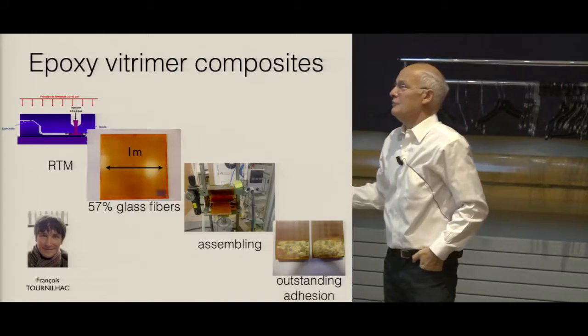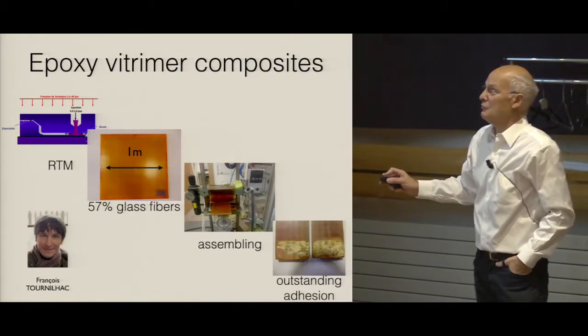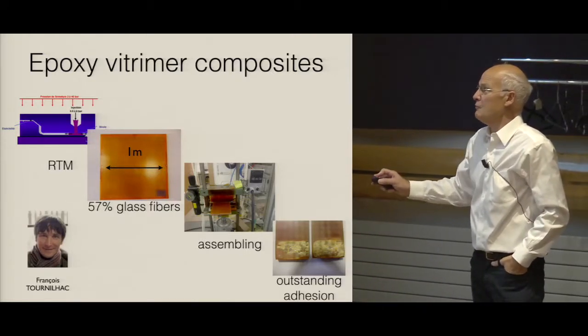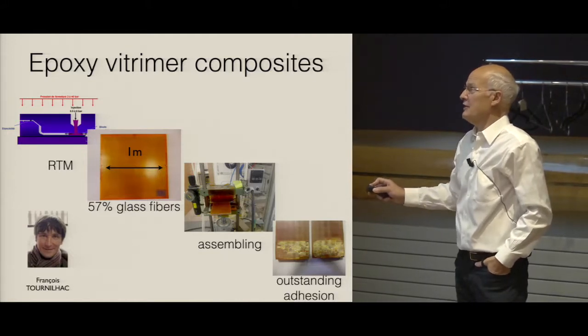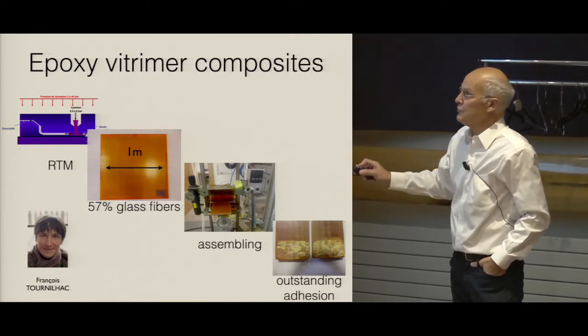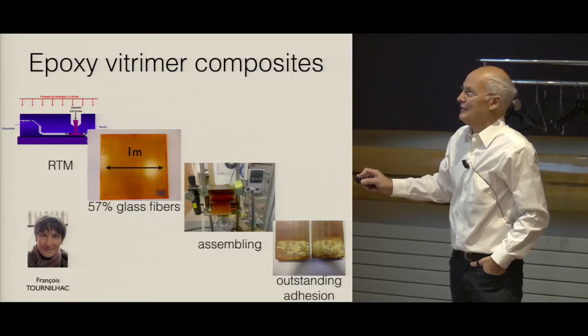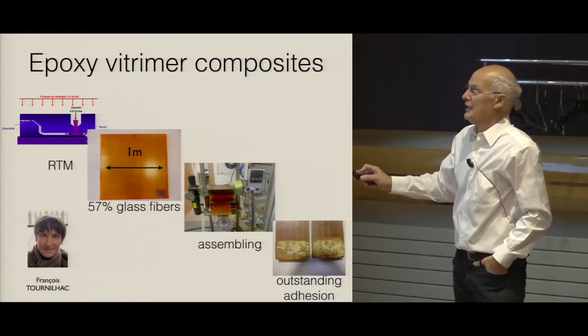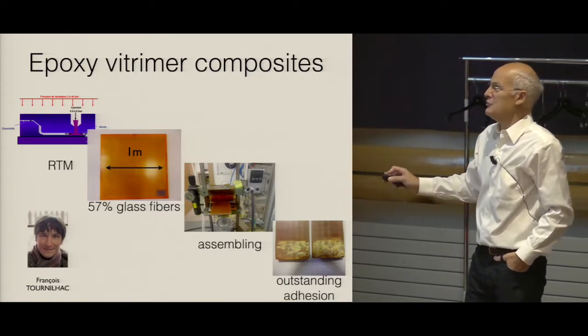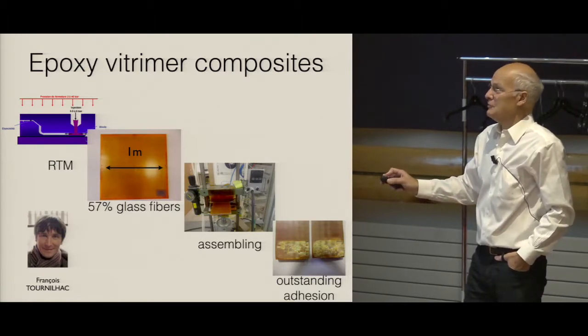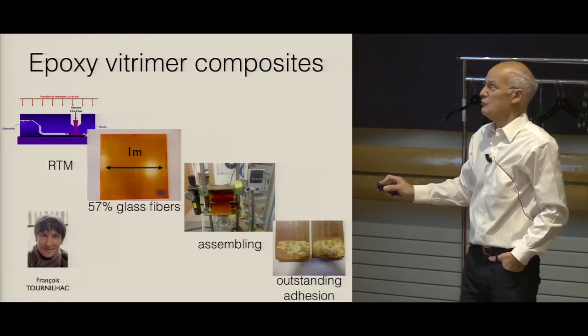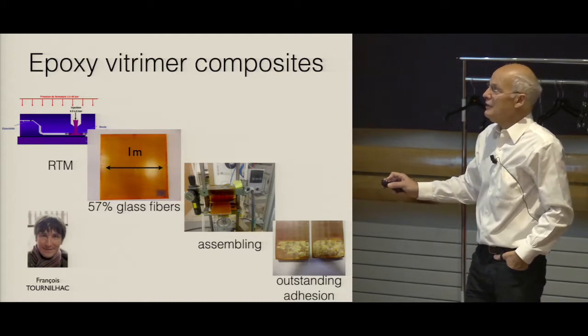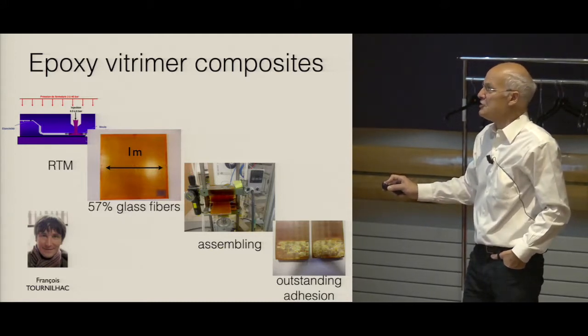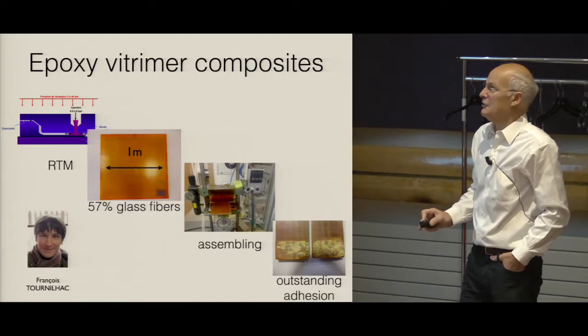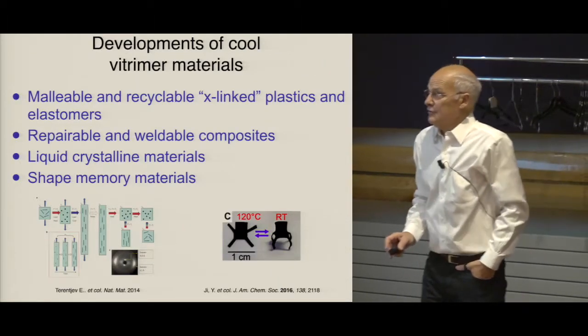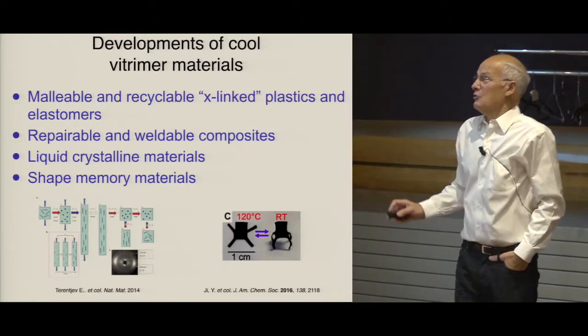And so because some like it hard, we also show that we can make composites. And again, with the composites, there are plenty of glass fibers, and this is important if you want to make light planes, light materials. So you have the resistance of a typical thermoset, the modulus of a typical thermoset, and then you can assemble it just by heating and adhesion. And this was in 2011, more or less.